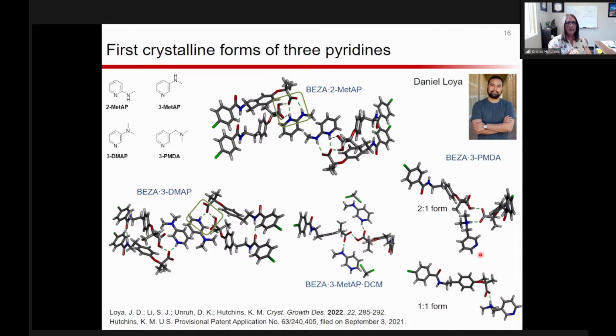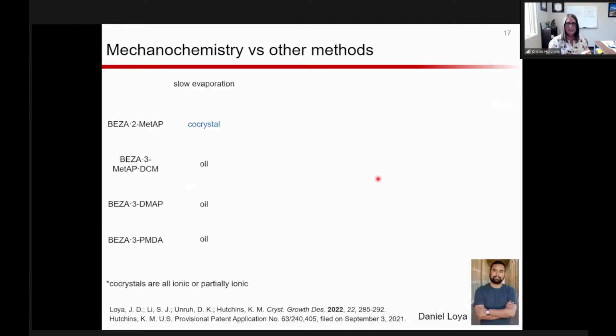And I'm going to walk you through how we actually found those 2 forms and were able to get one or the other. Just to summarize this, we initially started with slow evaporation methods. With all the 3 substituted, we got oils regardless of the solvent that we chose. In the case of the 2-methyl, with just one specific solvent, we were able to get a co-crystal, but the rest of the times we were getting an oil. So only one specific solvent will give you that co-crystal, whereas oils were very common prior to finding that solvent that worked.